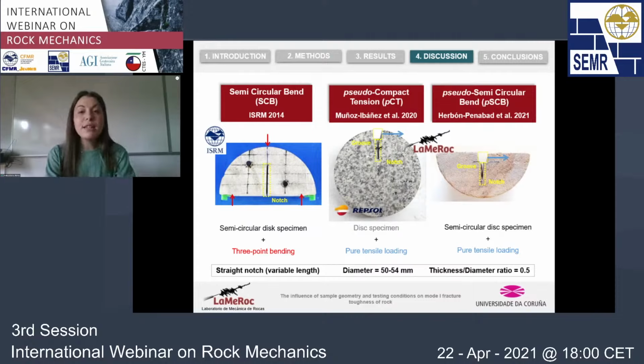So we have called this one the pseudo semicircular bend test, and we can see it as a combination of the other 2 methods. So you can see that the shape of the sample is a semi-disc, like in the case of the SCB. We also have the straight notch, but like for the PCT a wider groove in the upper part, so that this semi-disc can be loaded under pure tensile conditions.